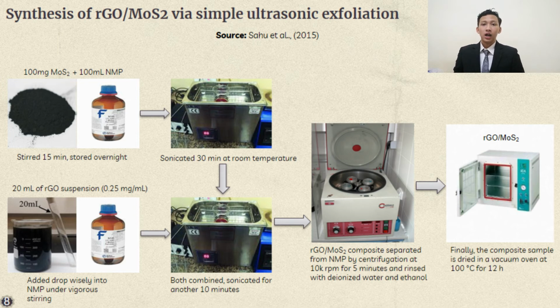In another beaker, under vigorous stirring, 20 ml of RGO suspension is added dropwise into NMP. Both solutions are combined and then sonicated for another 10 minutes. The RGO-MoS2 composite is then separated from NMP by centrifugation at 10,000 rpm for 5 minutes and rinsed with deionized water and ethanol several times. Lastly, the RGO-MoS2 composite sample is dried in a vacuum oven at 100 degrees Celsius for 12 hours.